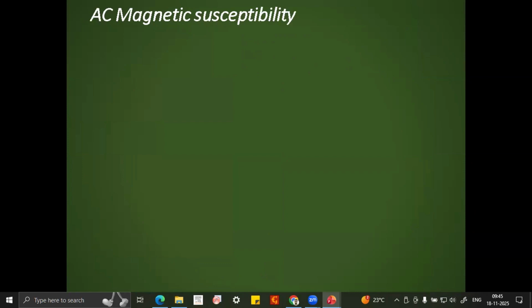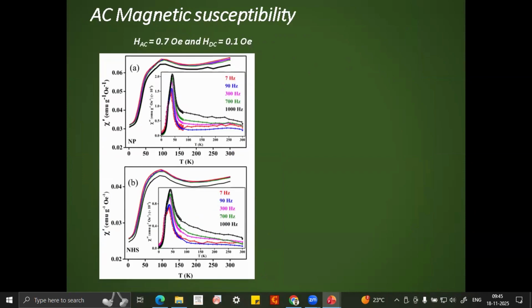Not gaining much information from the DC magnetic properties, we have also measured the AC magnetic susceptibility of our systems. This is the real part of AC susceptibility, and this is the imaginary part. This is for nanoparticle, and this is for nanohollow sphere.